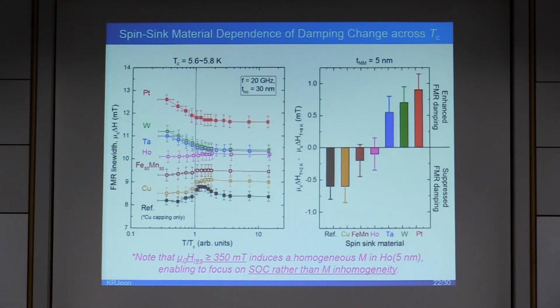In order to distinguish between these mechanisms, we have replaced the platinum layers with a variety of other spin sink materials. The left figure shows the FMR line width as a function of normalized temperature for various spin sink materials, obtained for the fixed niobium thickness of 30 nanometers and the fixed microwave frequency of 20 gigahertz. The right figure summarizes the spin sink material dependence of FMR line width change across TC. Here, positive and negative signs respectively indicate the enhancement and suppression of superconducting spin current in the superconducting state.